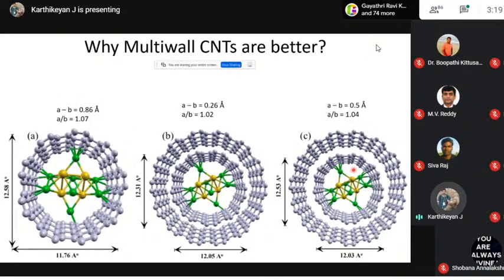Let us check the mechanical property. What is happening? Here I have measured the diameter along the X direction, A, and the diameter along the Y direction, B, for single-wall CNT as well as multi-wall CNT. As a case study, I have taken the Sn4Li8 system. For a single-wall carbon nanotube, the difference between A and B, that is, the deformation of the CNT, is very large. The difference is 0.86 Angstrom, and the A by B ratio is 1.07.